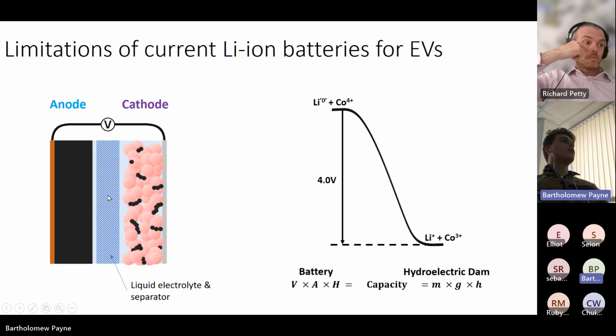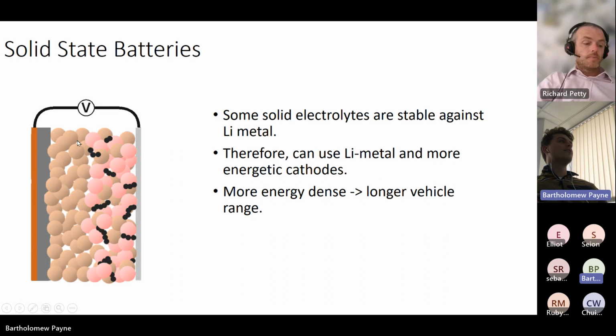And the research I do is actually replacing this liquid electrolyte with a solid electrolyte, which allows lithium ions to move through it but is electrically resistive, so electrons still go through the circuit. And some of these solid electrolytes are stable against lithium metal and stable against more energetic cathodes.